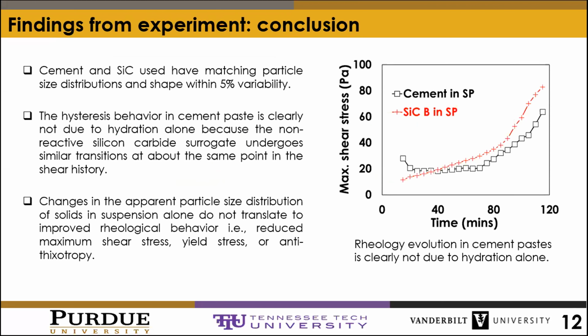So what are the broad conclusions to be made in this study? The stable rheological condition of Portland cement paste under shear is antithixotropic, not thixotropic. With the comparable rheology observed for non-reactive silicon carbide paste and reactive cement paste, it is difficult to suggest that changes in cement flow rheology in the first 120 minutes after mixing are the effect of hydration rather than particulate interaction. And finally, although certain additives in dilute systems significantly alter the apparent particle size distribution of particles in suspension, that observation alone cannot be used to produce a predictable rheological outcome.